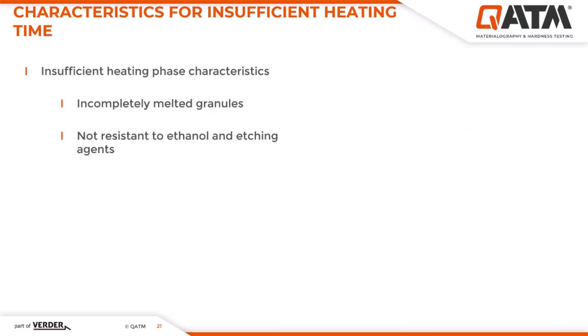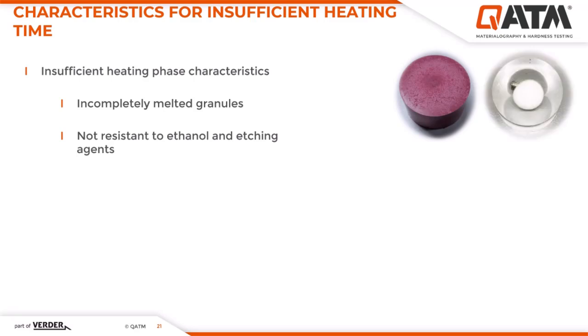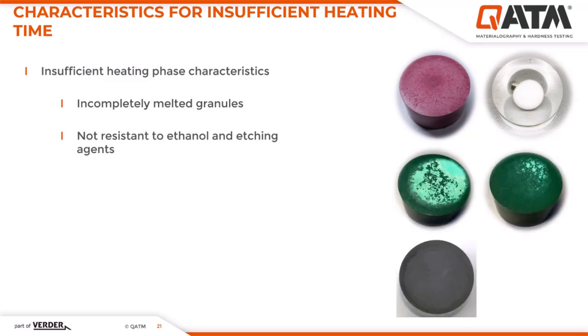As already mentioned, the mounting process can be divided into two phases, the heating phase and the cooling phase. One way to optimize the process is to shorten the heating time. If you start reducing the heating time, you will notice at what point the mounting material is no longer fully cured. If after mounting you see unmelted grains or a cloudy area in thermoplastic resins, you reached the minimum heating time, and in this case you have to slowly increase the heating time to remove these problems. A simple test is also helpful.